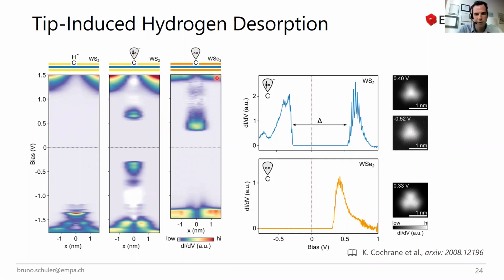Now you can do the same thing also for tungsten diselenide. And there the picture is slightly different. So first of all, if you start out with CH, this one is also negatively charged, but now if you remove the hydrogen, this thing becomes neutral. So we see this, for instance, up here in the conduction band, so there is no band bending anymore. And you just have a single state, which is now completely unoccupied. So it looks fairly similar, but again, you just have one state and there is nothing here. And we attribute this to a non-occupied dangling-bond-like state of this carbon impurity.